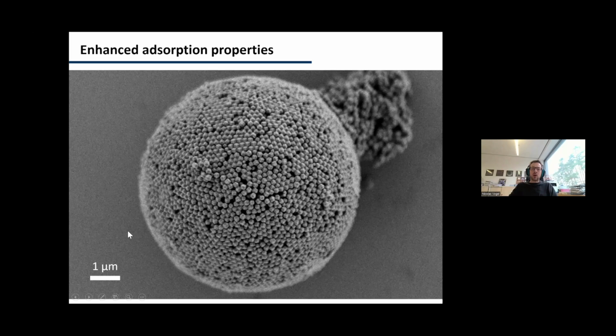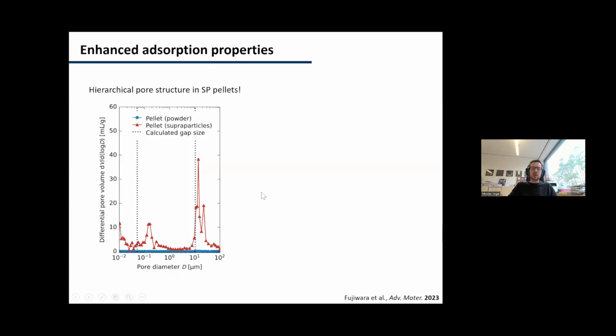This is how such a particle looks. So you see we are able, or our collaborators, Professor Watanabe from Japan, are able to make these particles very precisely. And if we now look at the gas adsorption properties, we see that we have different pore sizes. So we have the interstitial sites of the primary particles, and we have these very large pores that relate to the packing of the superparticles.